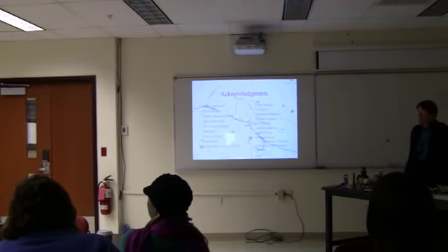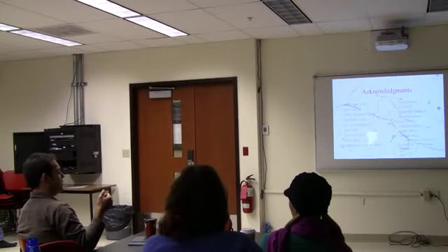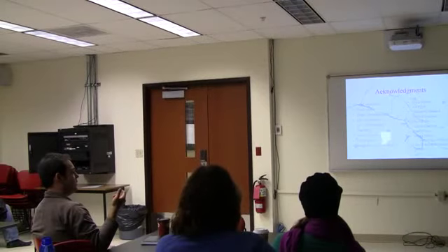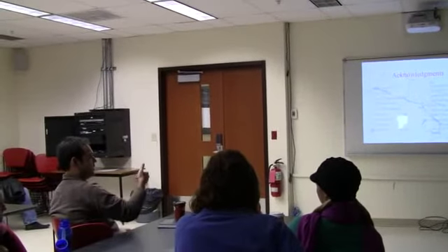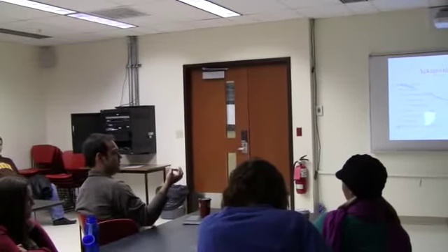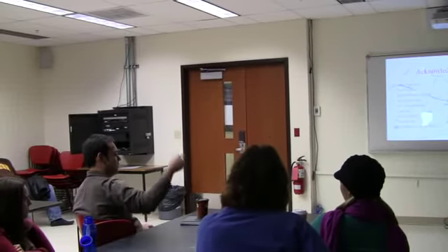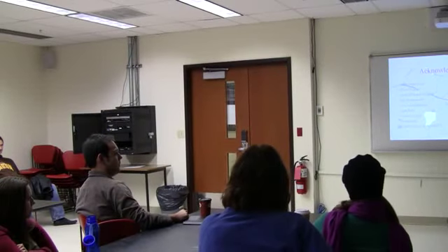I have a question about the porosity graph you produced. You have on one axis the porosity that you figured out using your computer programming. The imaging, yeah. So is that a 2-dimensional porosity that you compare areas? Yes. Now the other technique, does it compare a volume porosity? It's looking at a volume porosity, yes. So do you apply a 2/3 correction power factor? Not typically. If you're comparing areal porosity, then it's r squared for a sphere, right? But for volumes, it would be r cubed, would it not? So you would actually just take one porosity and put it to the power of 3 halves. We haven't done anything like that.